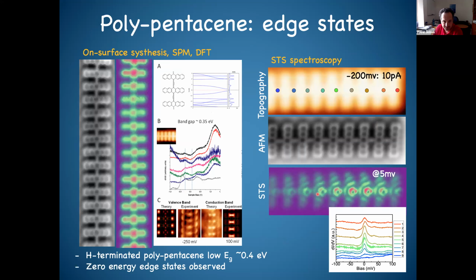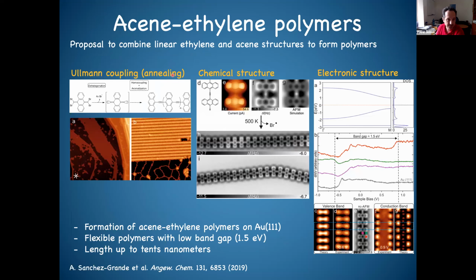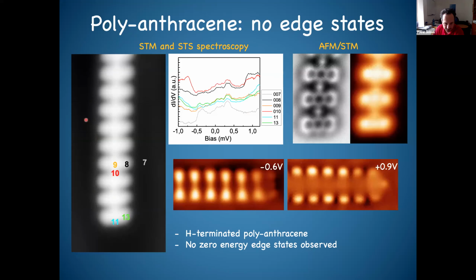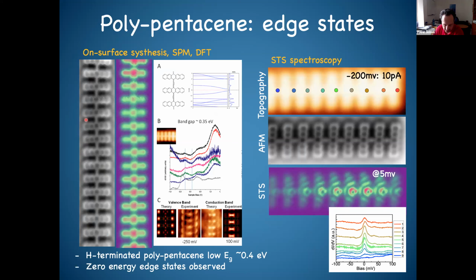So now let's do the same experiment, but we start with slightly different systems. Sorry, I omit the precursor here, but like before, instead of anthracene we now have a pentacene. We use the same reaction on the surface. Again, the pentacene is decorated by 4 bromines, and the procedure is the same. We put it on the gold surface and anneal it, and then at a certain temperature we start to see the growth of these very extended polymers, which are now made of pentacene instead of anthracene, made of 5 benzene rings.